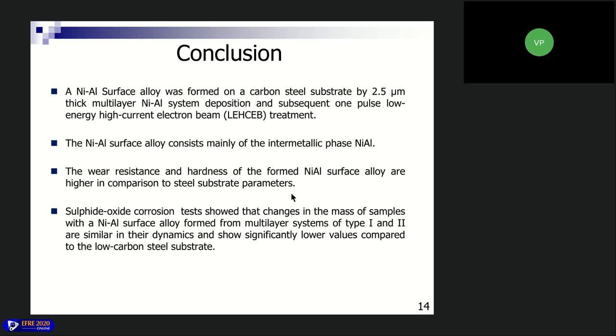It has been shown that the surface alloys consist mostly of the intermetallic nickel aluminum phase. The mechanical parameters, the wear resistance and hardness of the formed surface alloy are higher in comparison to the substrate parameters. And the tests of sulphide-oxide corrosion and high temperature oxidation showed the best results for the surface alloys in comparison with the substrate. So that's all.